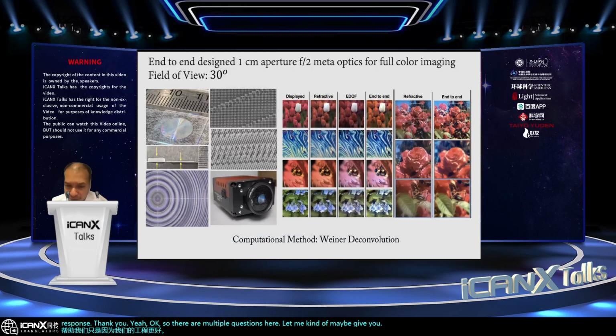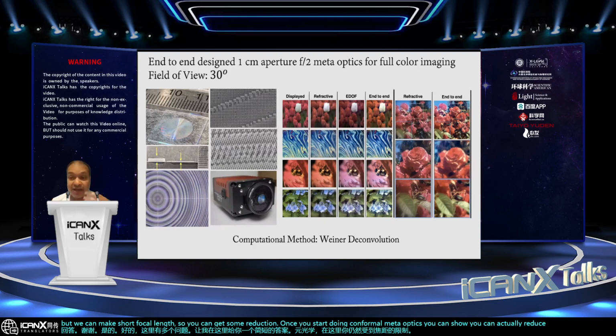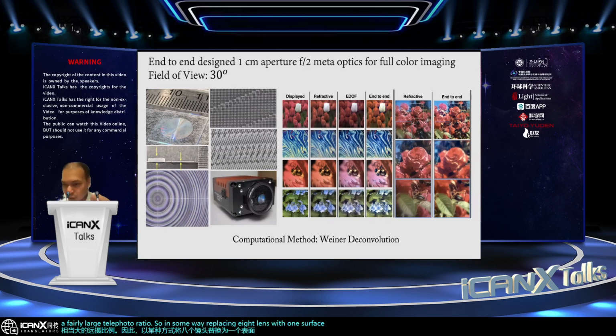Meta optics altogether here, you still are limited by the focal length, but we can make short focal length, so you can get some reduction. Once you start doing conformal meta optics, you can actually reduce the total track length because you can get a fairly large telephoto ratio. So in some way, replacing 8 lenses with one surface is probably not going to happen. But replacing these 8-9 lenses with the conformal meta optics, maybe 2-3 surfaces, can give you a much more significant reduction, right?